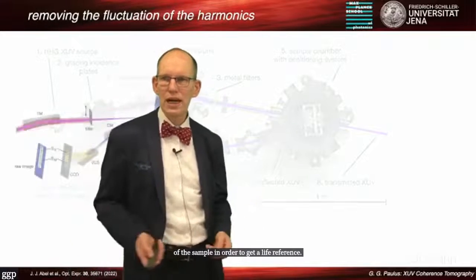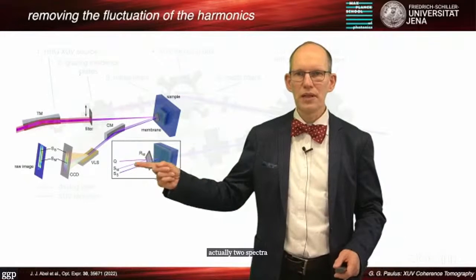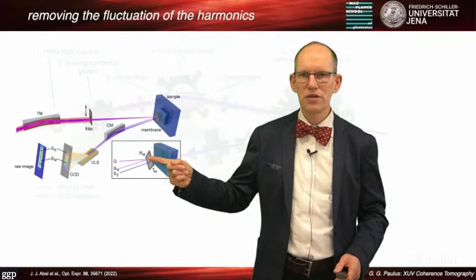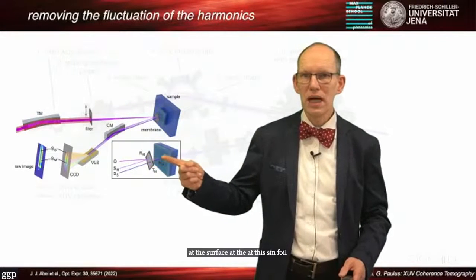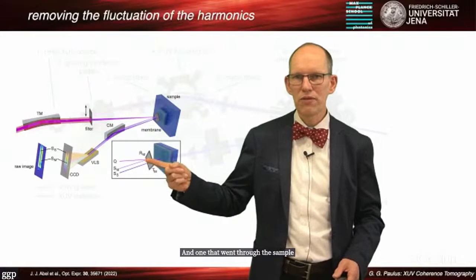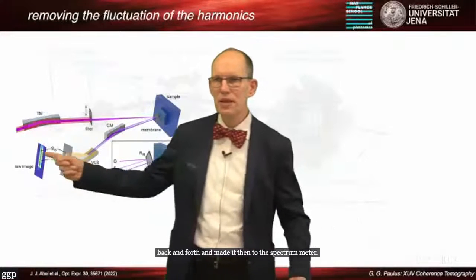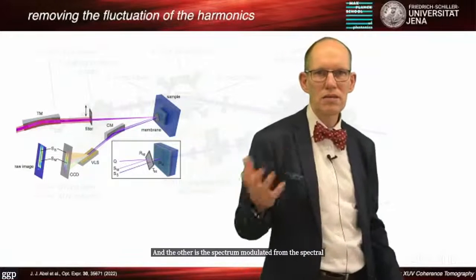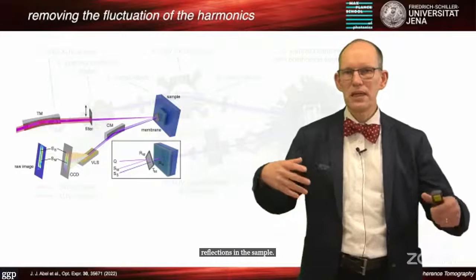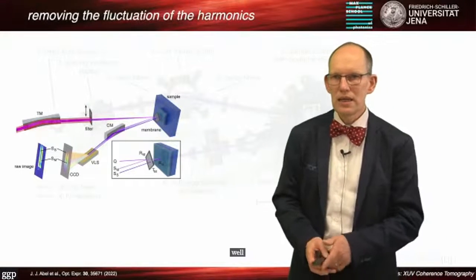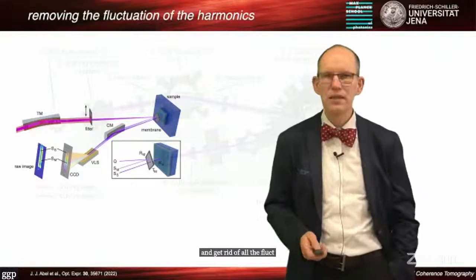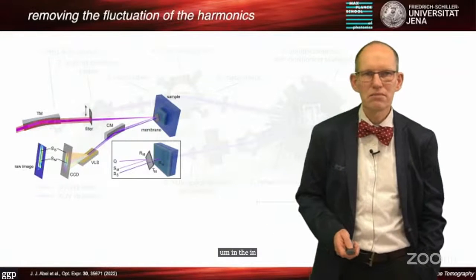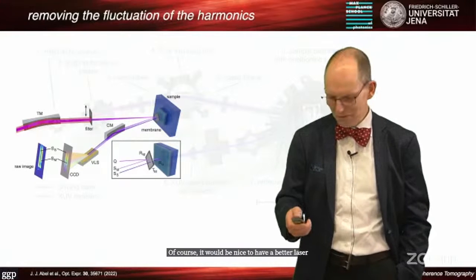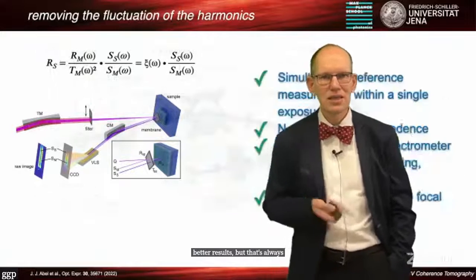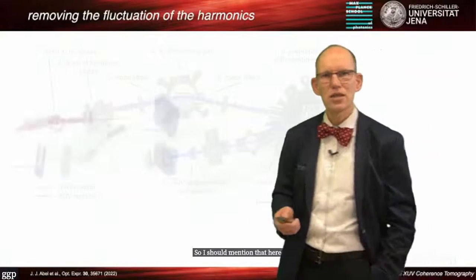So we record on the camera actually two spectra. One was reflected at this thin foil in front of the sample, and one went through the sample, back and forth, and made it then to the spectrometer. So you see that we have two spectra. One is the reference spectrum, and the other is the spectrum modulated by the spectral interferences due to the internal reflections in the sample. With this, we can normalize and get rid of all the fluctuations that we have in the high harmonics. Of course, it would be nice to have a better laser, then we would have even better results, but that's always the case. So this is how you do that. I should mention that here, just to show the difference.